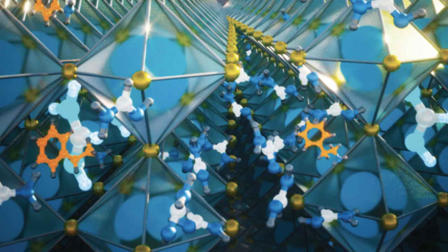First, the researchers exposed the pre-treated samples to 100 degrees Celsius for 40 minutes and then measured their changes in chemical composition using X-ray photoelectron spectroscopy. They also used another type of X-ray technology to investigate precisely what type of crystal structures form on the film's surface. Combining the information from the two tools, the researchers could visualize how the cations diffuse into the lattice and how the interface structure changes when exposed to heat.